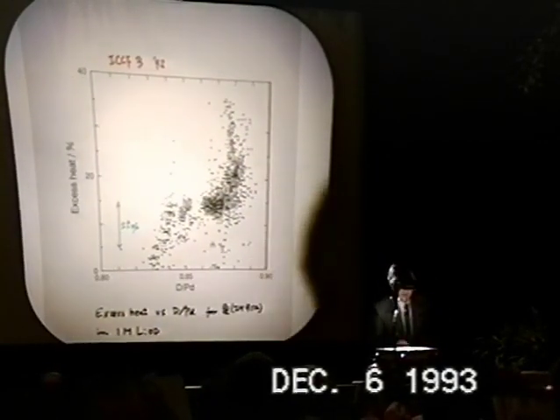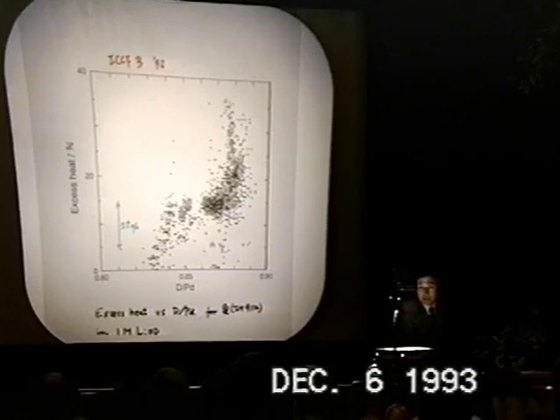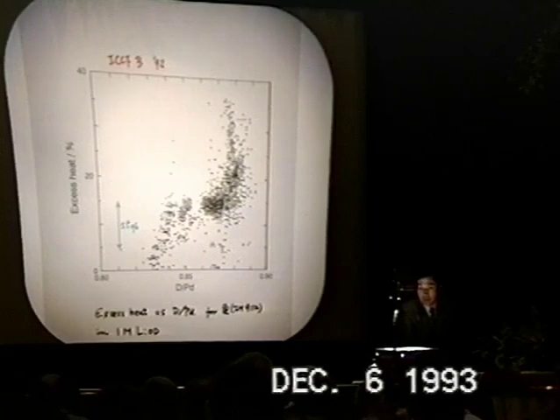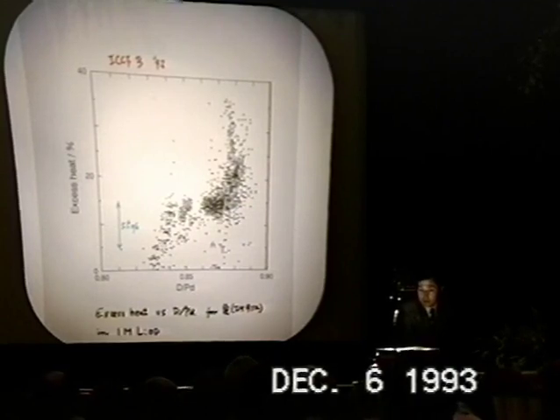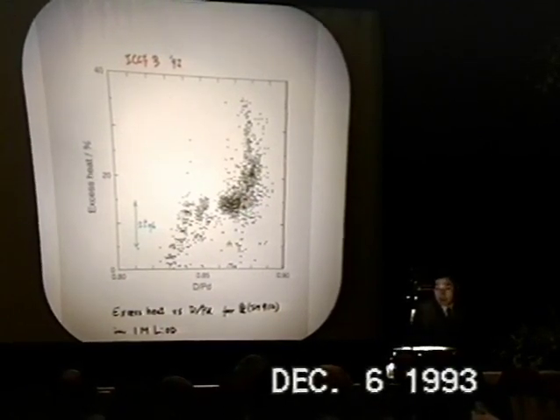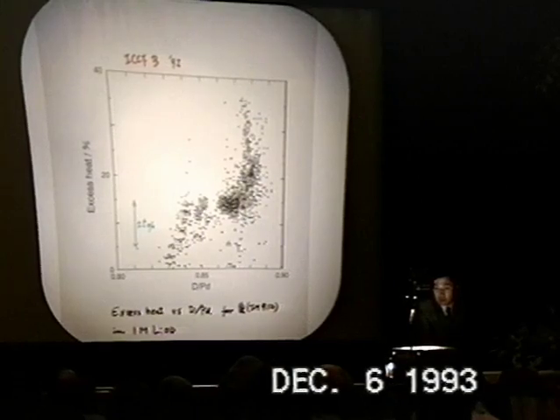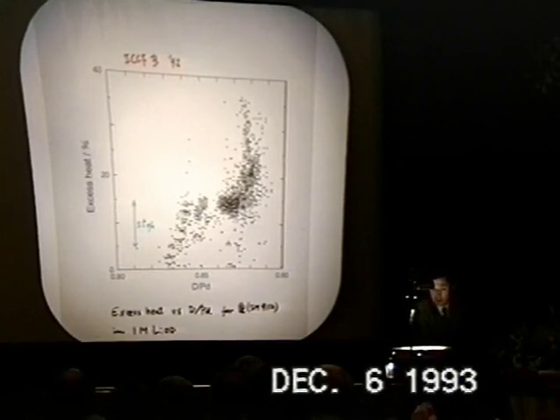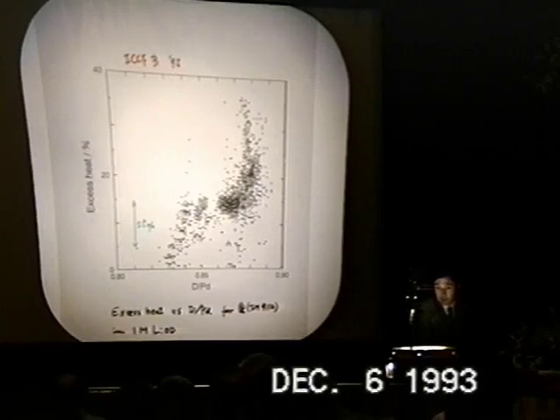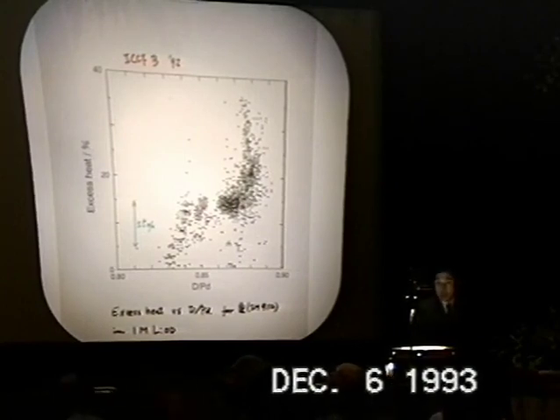So probably many of you remember this data, which we presented at the Nagoya conference last year, giving the excess heat as a function of deuterium loading ratio. So in this figure, we meant to show that excess heat is generated as a function of deuterium loading ratio from somewhere around 0.83 or 0.84, and increases steadily with increasing deuterium loading ratio.